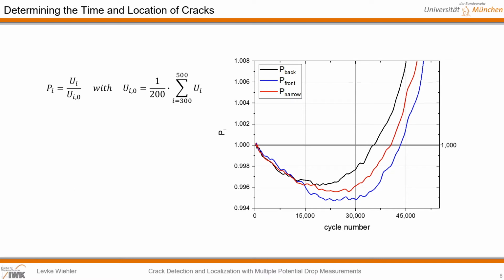Because the tests differ, for example, due to the quality and the exact location of the welding spot, the absolute measurement results vary and are therefore not comparable with one another. To remedy this, the measurement results were standardized by dividing the potential difference Ui by the initial voltage Ui0, defined as the mean value of the potential of 200 cycles at the beginning of the experiment. On the right side you can see the run of the relative potentials.